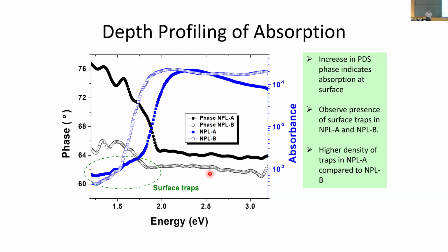But when you look at the phase angle for this particular sample, there's a small rise here, not much in terms of angle, but for the other sample, the phase rise is huge. So what this corresponds to is the absorption from the top of my sample.